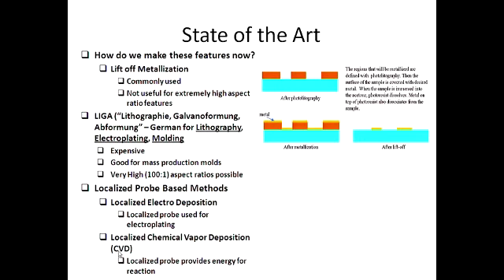At first, we have a layer of photoresist and expose that. We have the pattern. After that, we deposit metal on the photoresist layer, and after finishing deposition and cleaning, we have the pattern in this shape. This is a very good and very common method, but it's not possible to use when we need high aspect ratio, because having a very thick layer of photoresist is not possible. It's hard to manage the deposition and also cleaning at the end.